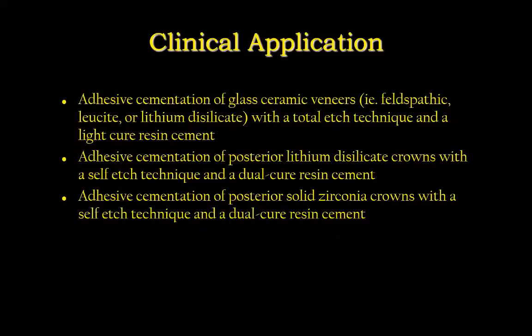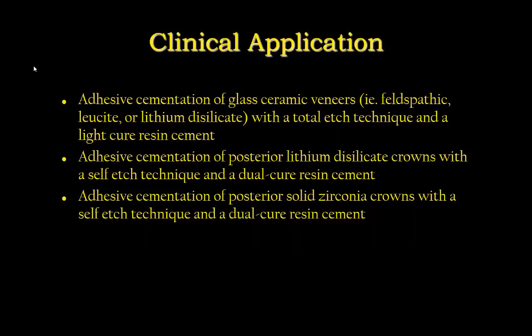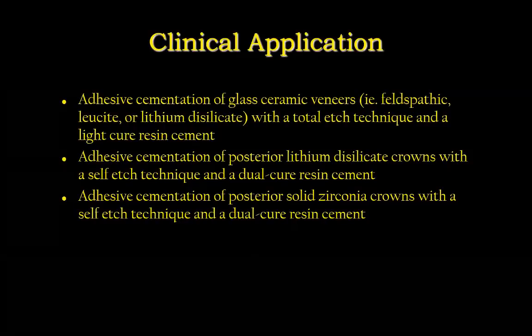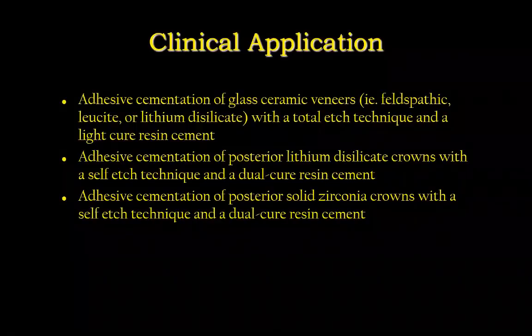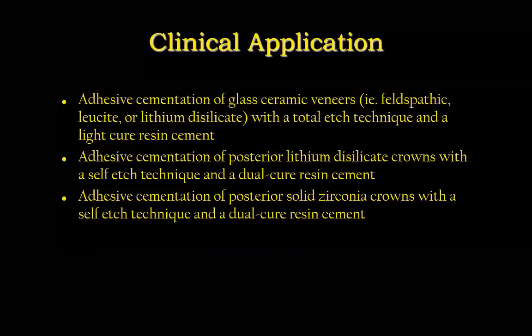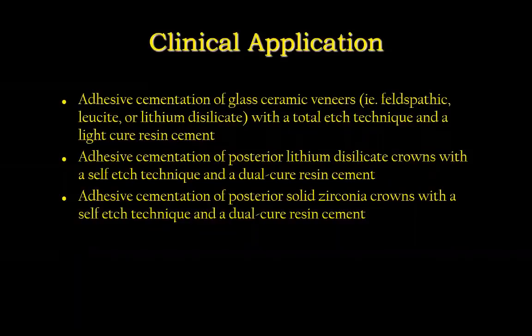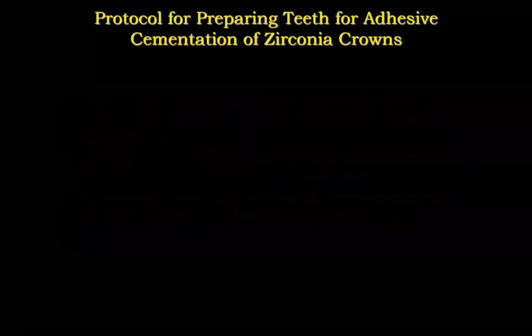Zirconia has an affinity for phosphate. That's good. That's why the MDP monomer, which is an acidic phosphate monomer, works so well with zirconia. It has an affinity for phosphate. Zirconia does. So anything that contains any type of phosphate monomer is going to bond well to zirconia. So that's why these new primers like Z Prime Plus contain that MDP monomer. So you're going to get higher bond strengths there. But your saliva contains phospholipids, and these phosphates in the saliva will adhere to the zirconia, and it'll interfere with bond strength. So you've got to clean that out. And that's why you use the Zirclean or the Ivaclean.